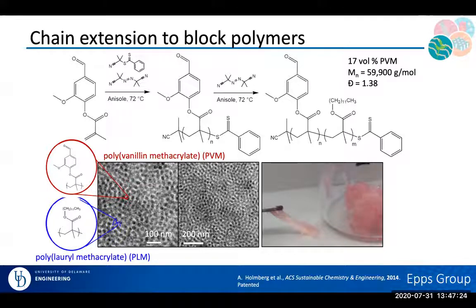So in this particular case, we could do TEM, or transmission electron microscopy, look at the different types of nanostructures that were formed. And if you remember, one of the things that we're interested in was spheres of a hard material, so that lignin-based methacrylate shown as the dark dots, in a matrix of a soft material, such as the lauryl methacrylate, which is shown in the light due to staining. And so what that then leads to is a nice, very tacky material that we've been able to publish and patent, and we have several licensing opportunities that we're actually pursuing with this material because it has properties very similar to the adhesives that you would find on the back of sticky notes.